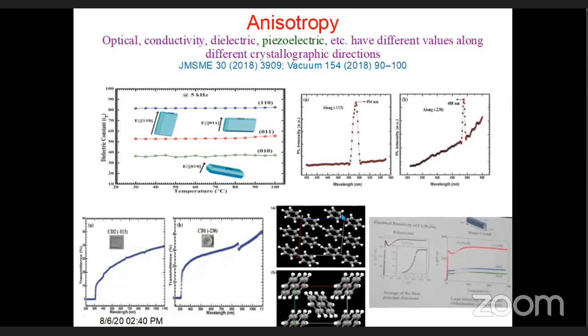Similarly, the UV transmittance is very anisotropic. In one direction, it can show a transmittance of 50%, while in another direction, it is as low as 4 to 5%. So these anisotropic properties are the characteristic of crystals. This change in property in different directions is not observed when we are working on a ceramic or polycrystalline material or even a thin film.